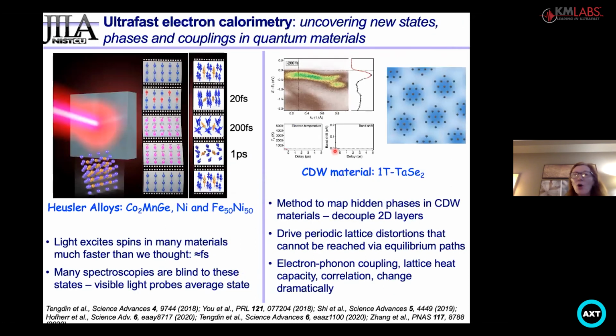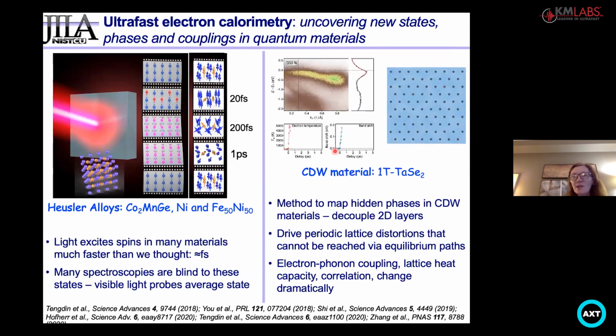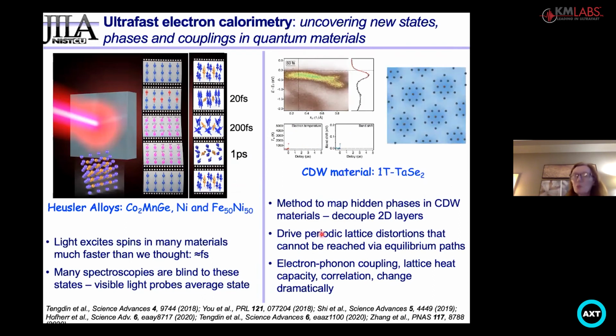So the way to think about it, and this is something we've shown now in several systems, is that the heat capacity of the electrons is smaller than the lattice. So if you monitor the electron temperature, whenever there's a change in coupling or a phase transition, you should see a jump in electron temperature. And we're seeing that that is allowing us to find new excited states in magnetic materials and make beautiful maps of 2D materials, charge density wave materials, because it allows you to find hidden phases that you could not see otherwise. So let me explain and also look at